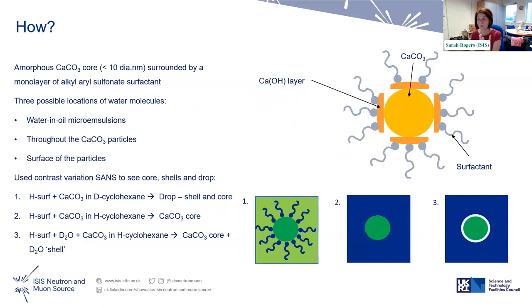One was that they form water-in-oil microemulsions. One is that it's just somehow dispersed throughout the calcium carbonate particles. And the other one was that it could be on the surface of the particles. So we designed this experiment with different contrasts. So we did H surfactant with D oil, sometimes all H, and then a mixture of the two. And then we added D2O to some of them to work out exactly where the water goes. So that would be the idealized picture. So that's where you can see everything. That's where you can just see the core.